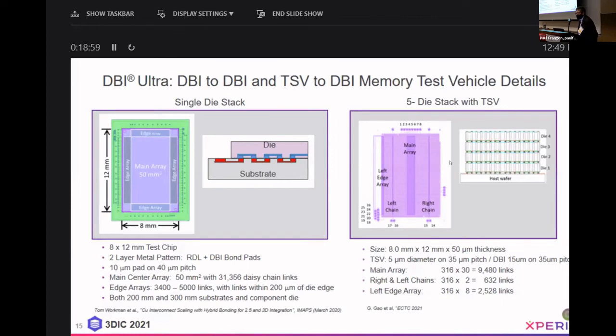And in this case, we have 4 different chains. One in the center has about 9,000 connections. One on the left and the right have about 600 connections on each. And then there's an edge chain that's about 80 microns from the edge, again, for evaluating edge effects. And it has about 2,500 connections in that particular chain.